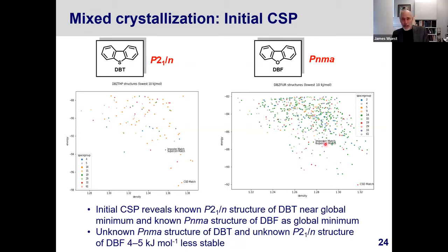So there's a clear challenge in this work. I mean, this faces the experimentalist with the potential existence of many different polymorphic forms, but the experimental evidence is that the thiophene crystallizes in this form and the furan crystallizes in this form, and nobody's seen anything other than that. How do you get these other structures? The unfortunate thing is that you can see from this prediction that if you put the furan into the thiophene structure, it matches one of the predicted structures, but it's 4 to 5 kilojoules less stable. And if you put the thiophene into the furan structure, you find it as a predicted structure, but again, it's highly unstable relative to the global minimum.